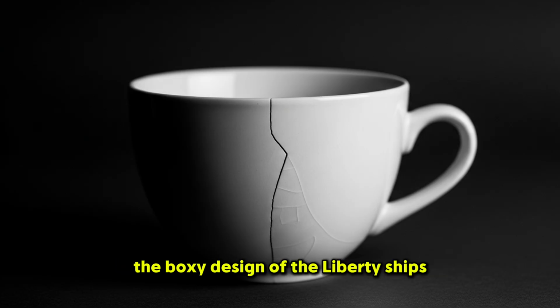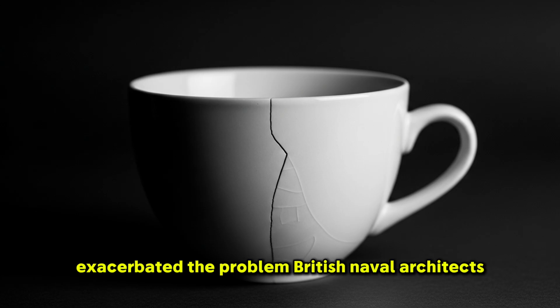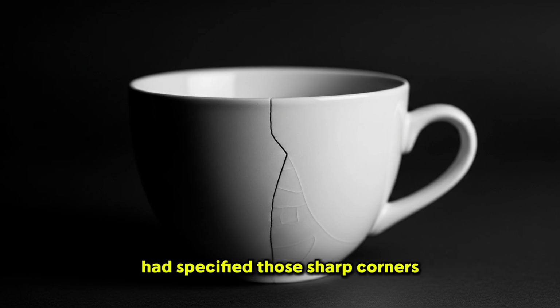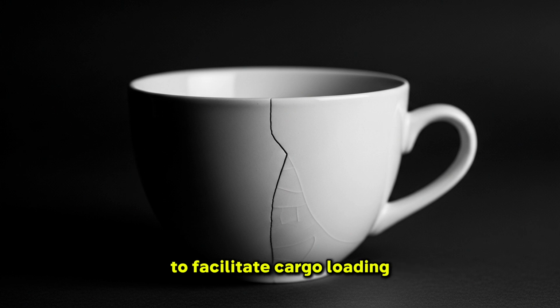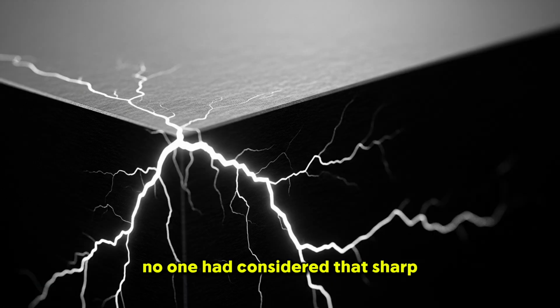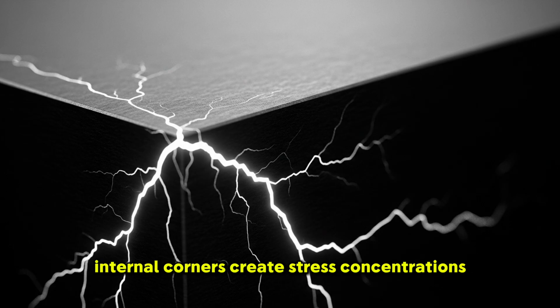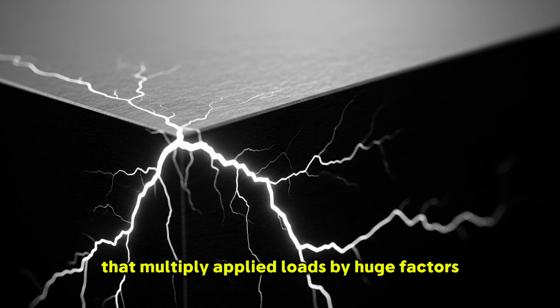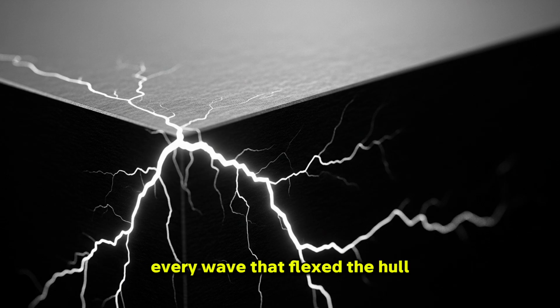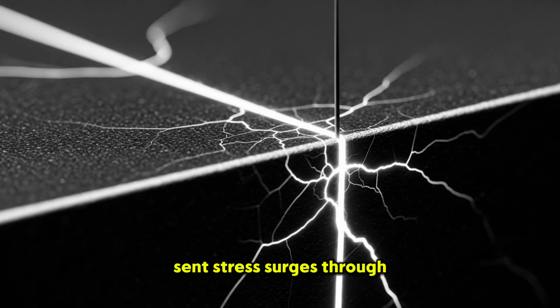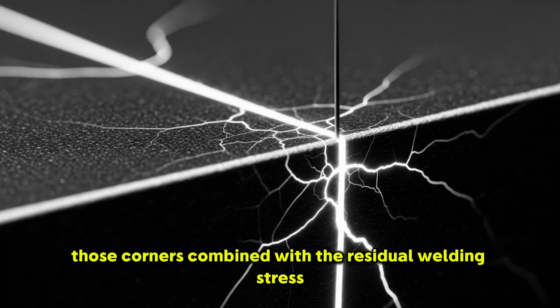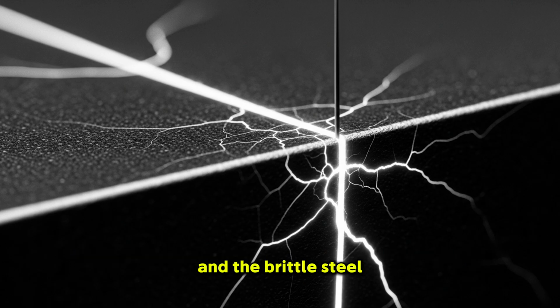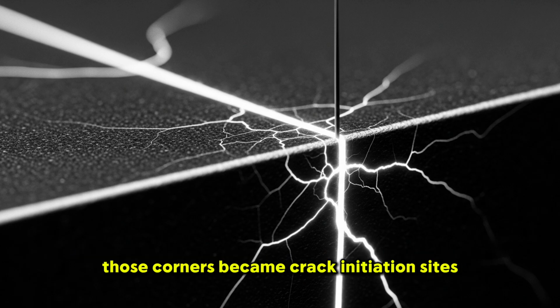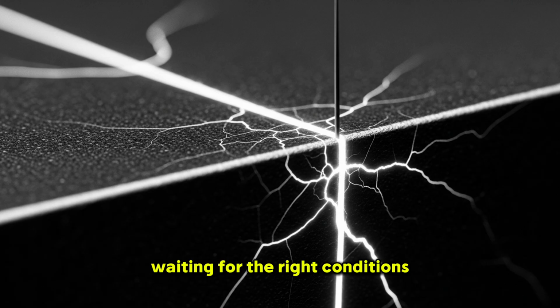The boxy design of the Liberty ships exacerbated the problem. British naval architects had specified those sharp corners to facilitate cargo loading. No one had considered that sharp internal corners create stress concentrations that multiply applied loads by huge factors. Every wave that flexed the hull sent stress surges through those corners. Combined with the residual welding stress and the brittle steel, those corners became crack initiation sites, waiting for the right conditions for catastrophic collapse.